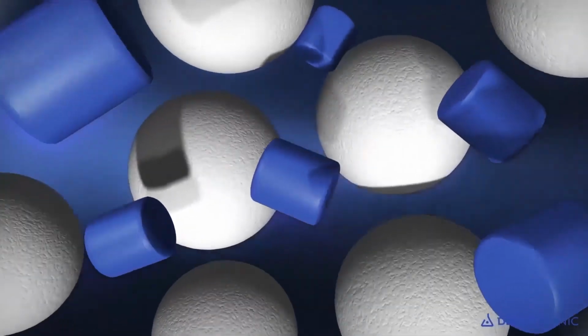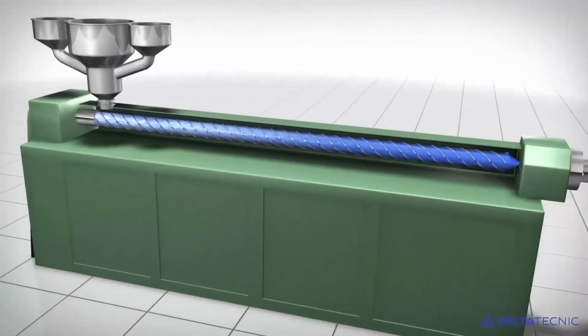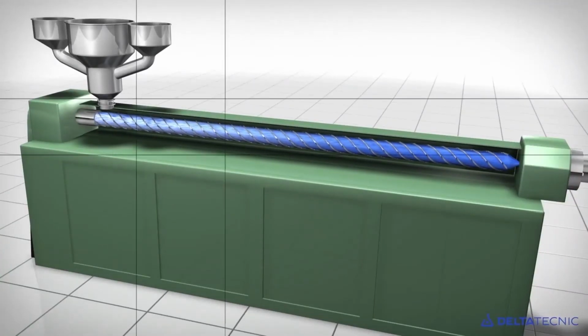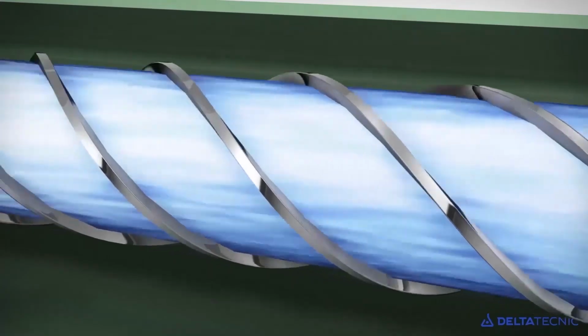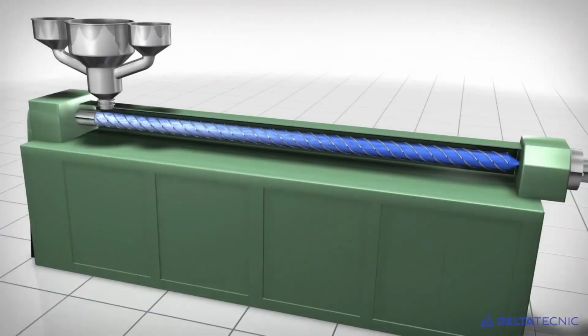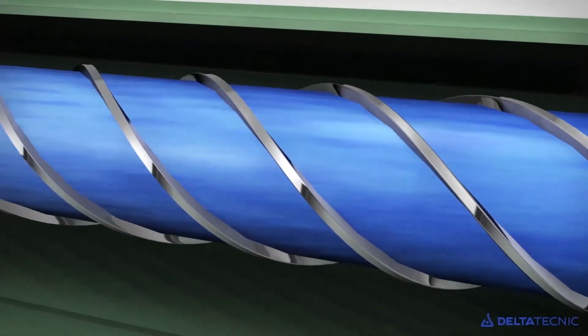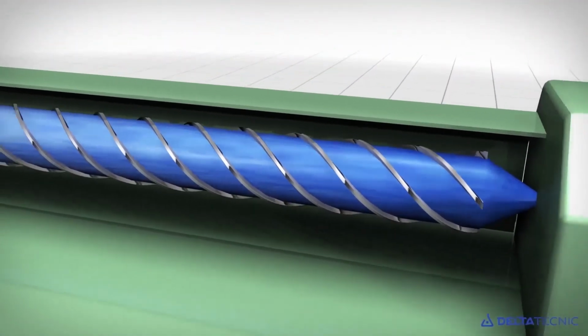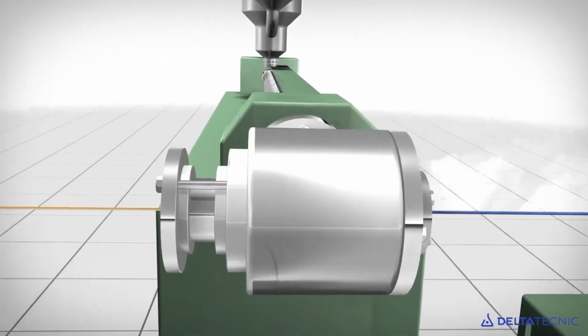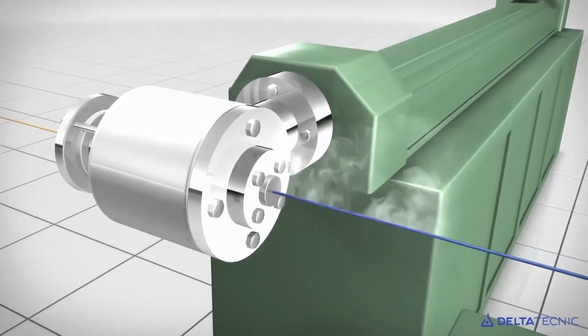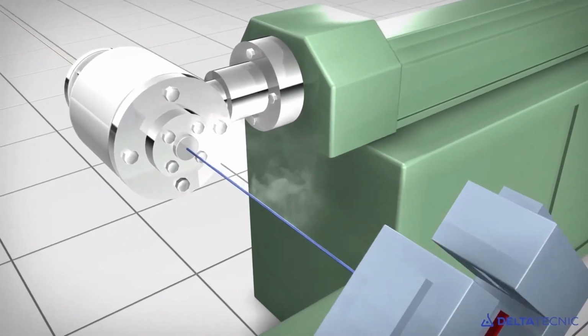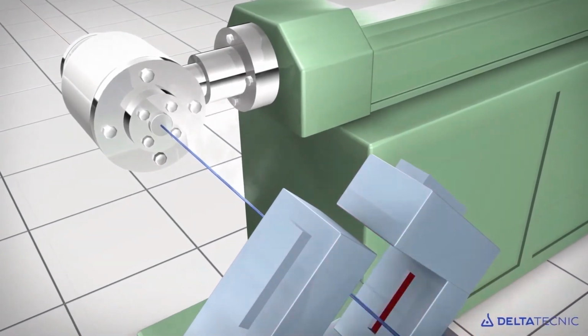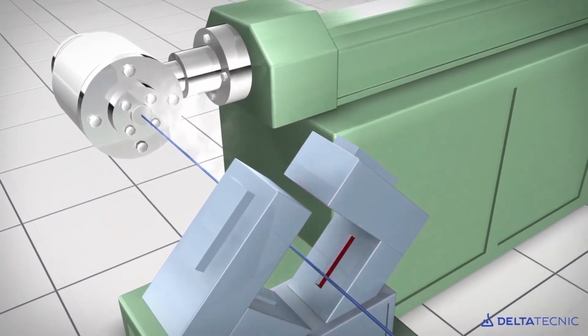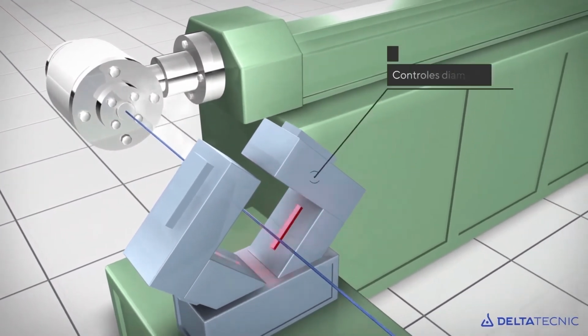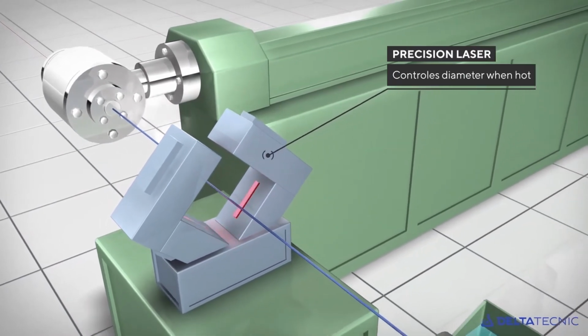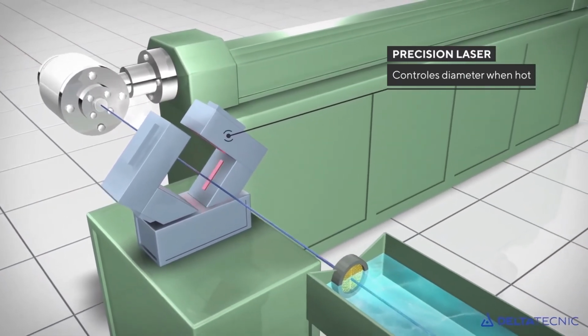So in this video, as you see now, in this first example, the size of the color pellets is quite similar to the size of the compound pellets. In some cases, when the size of the pellet is similar to the size of the compound, the color does not completely melt during the extrusion process. And here we see a simplification of a cable manufacturing process. You see here the extruder head, and here you see the layer on the cable manufacturer. You see the different laser control units, the cooling basin, and so forth, the spark test later on.